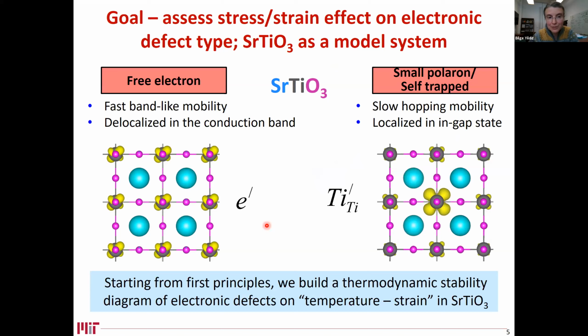So what do we mean by this? Different electronic defect types in strontium titanate, and how strain could change their relative stability. So the two different electronic defects that we refer to here are the free electron and small polaron. By free electron, we mean delocalized electrons in the conduction band, which have fast band-like mobility, versus small polaron, which is a localized electron on the titanium cation, which forms a localized in-gap state and shows hopping mobility, which is slow. Okay?